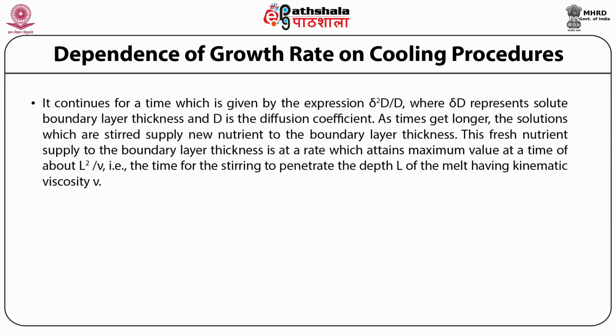It continues for a time, which is given by the expression delta square by D, where delta represents solute boundary layer thickness and D is the diffusion coefficient. As times get longer, the solutions which are stirred supply new nutrient to the boundary layer. This fresh nutrient supplied to the boundary layer is at a rate which attains maximum value at a time of about L square upon v. That is the time for the stirring to penetrate the depth L of the melt having kinematic viscosity small v.